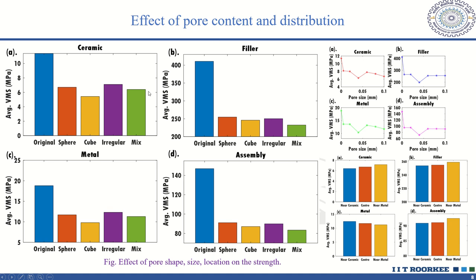And then the effect of pore content: the real world assemblies contain different shapes of pores, different sizes of pores, and at different locations in the joint assembly. So we design different shapes, that is sphere, cubical, irregular, and mixed, meaning containing both irregular and regular shaped voids. And then performed the thermal stress analysis. It is found that the joint assembly containing a mixed combination of pores, that is a mixture of irregular and regular shaped pores, possesses the minimum average thermal stress or can bear higher thermal stress.